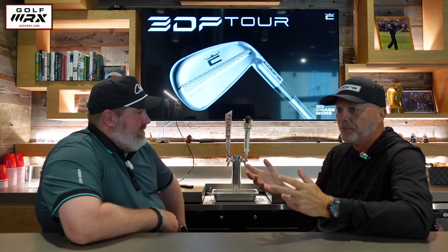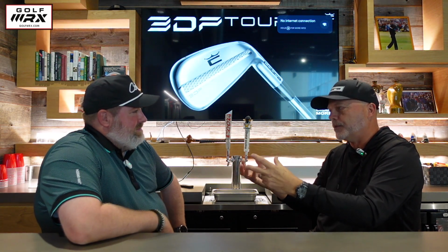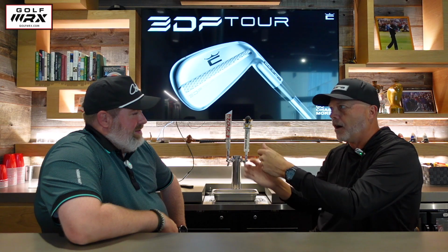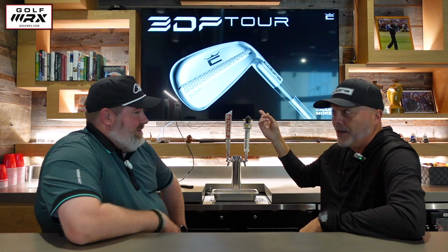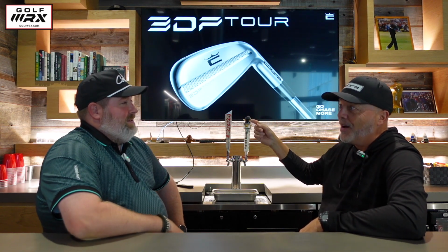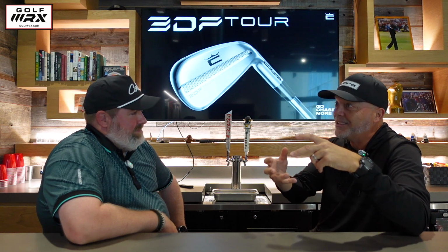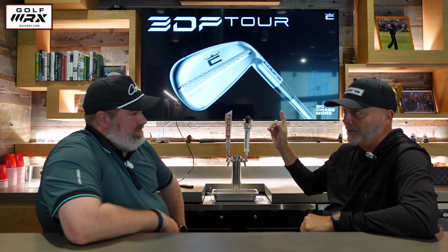So you've got to figure out, okay, how do I build this so it doesn't need any support structure in the inside? And 3D printing now, as you said, is pretty ubiquitous, so you see it all over the place. You'll see 3D printing machines where there's a structure that's holding up the actual part, and the structure's built at the same time. Then when it's done, you snap that structure off or sand it or whatever, and there's your part. We can't do that because the lattice is on the inside. You can't get to any support structure. So on top of figuring out how to polish it, also figuring out how you're going to build it such that when it comes out, you can pour the powder out of it, and the lattice has structural integrity. Right? So that was a big deal. There was a whole bunch of manufacturing things that had to be done to make this.